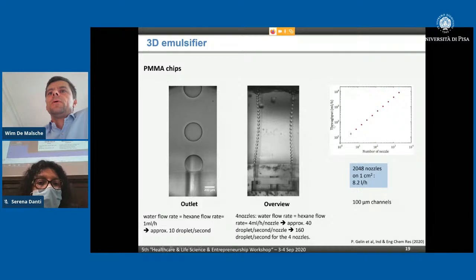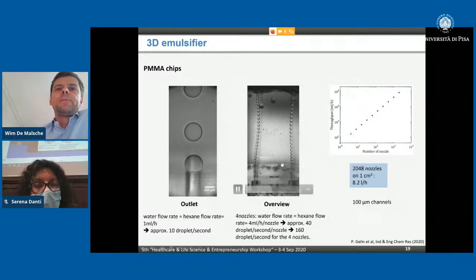And then to give you an impression of the throughput, here we're plotting the number of nozzles against the throughput. If we look at throughput and footprint, you can see we have a lot of space left, so we are in fact totally not pushing the density of the nozzles yet. But having a density like this, we can get close to 10 liters per hour on a 1 square centimeter device.